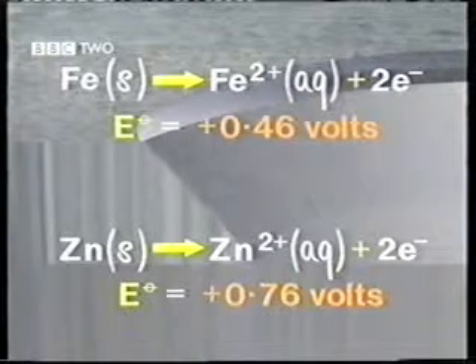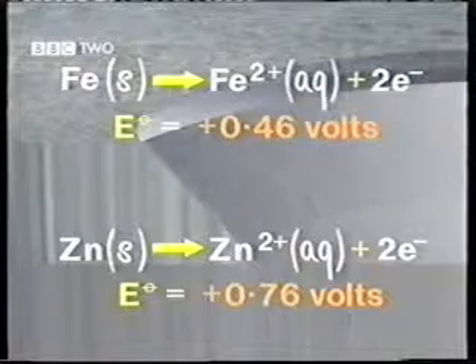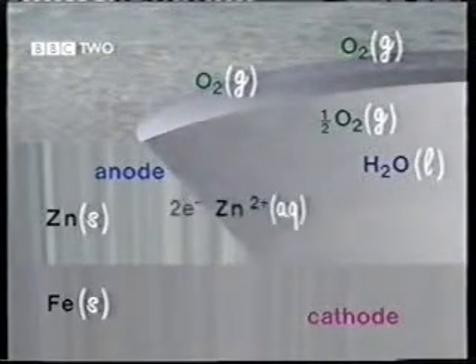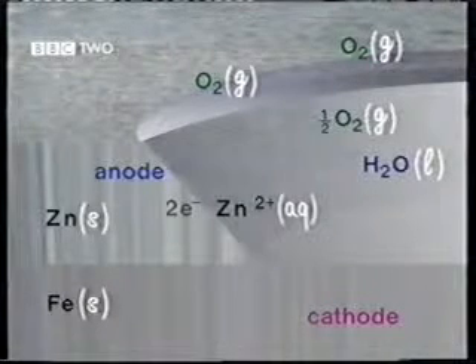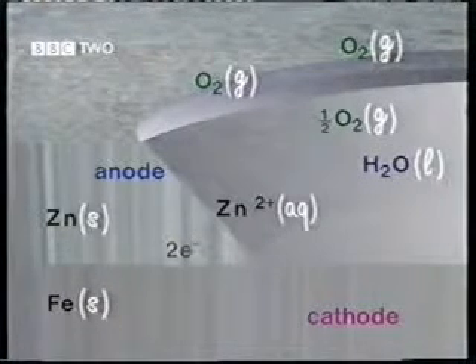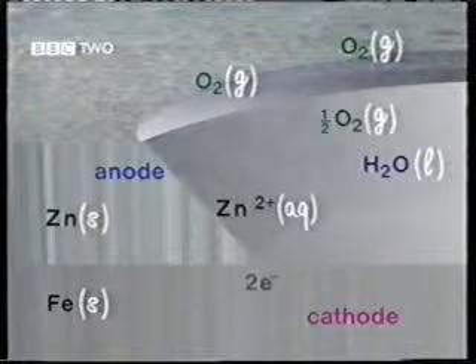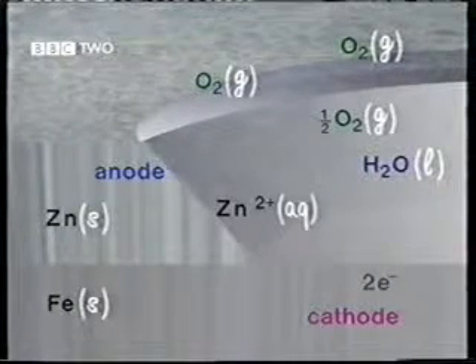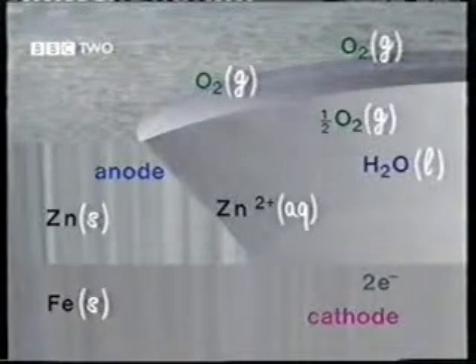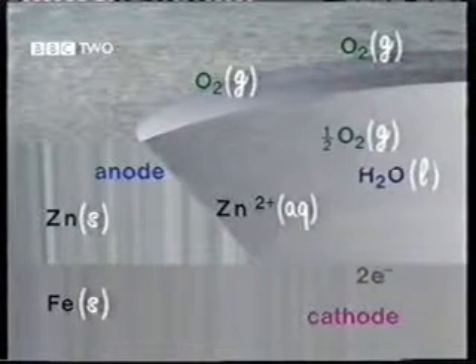With two metals present, there is the opportunity for one of two anodic reactions to take place. Either this one or this one. Preferentially, the latter reaction will occur, because the zinc is more electropositive than iron. And the kinetics are favourable too. So, zinc is sacrificed in the protection of iron, and in the anodic reaction it dissolves to form the divalent zinc cation. The cathodic reaction is the same as before, but this time it occurs predominantly on the exposed steel surface.